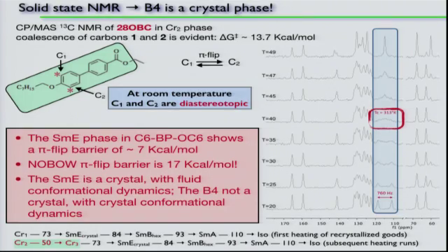All right, this stuff actually has a smectic E, but you can see that this is the top of the crystal 1 phase. So it's still a crystal up here, and you're seeing a singlet. So that means that pi flip is happening fast enough to be unable to observe the splitting. You can't resolve those two peaks because it's flipping too fast. That's in a crystal. So then you can keep heating up into a second crystal phase, and then you can go into a smectic E.